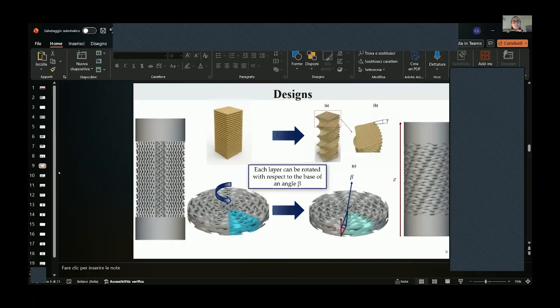Then we applied to the reference specimen the so-called Bouligand effect. As a Bouligand structure is a layered structure in which each layer is rotated with respect to the previous one, here we rotated each layer with respect to the base by an angle beta, which is a function of z, which is parallel to the axis of the specimen.